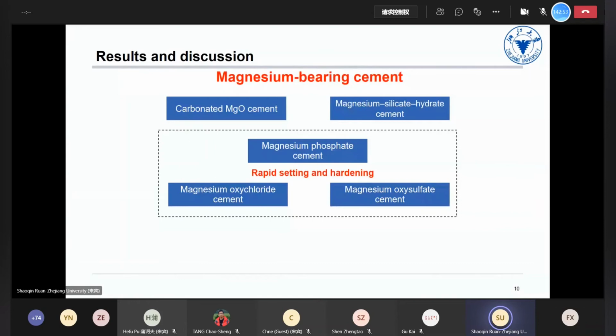Then, there are several types of magnesium-bearing cement, for example, carbonated MgO cement, magnesium silicate hydrate cement, magnesium phosphate cement, magnesium oxychloride cement, and magnesium oxysulfate cement. The magnesium phosphate cement, magnesium oxychloride cement, and magnesium oxysulfate cement all show rapid setting and hardening properties, which is quite useful in the process of SS. So they are commonly used in a lot of applications.